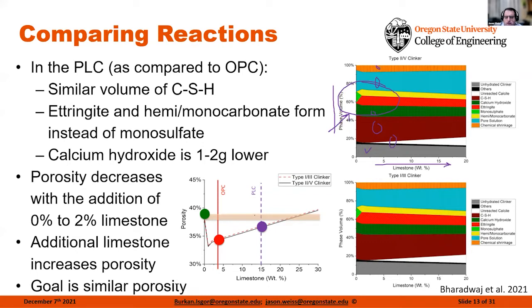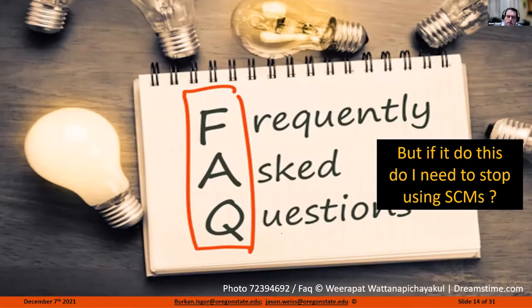So what we're able to do now is explain from first principles why adding limestone initially reduces the porosity and increases the strength. And then when we go to higher levels, we can actually produce the exact same strength that we had originally, but we can do it by producing 12 to 15% less CO2 for the exact same mixture. This is one of the reasons why Portland limestone cement is really picking up and being used so heavily. Further, we can actually start to answer questions that people frequently have, because people say, well, if I start using Portland limestone cement, should I stop using SCMs? And our answer to this question is unequivocally no.